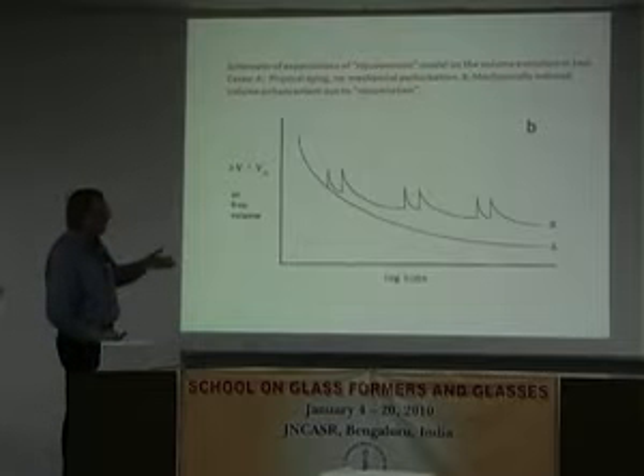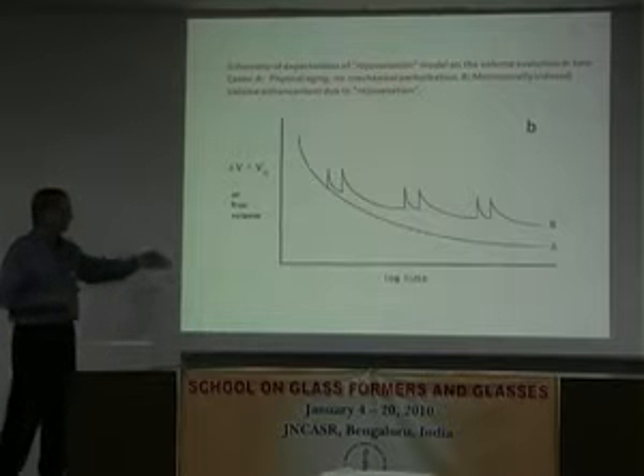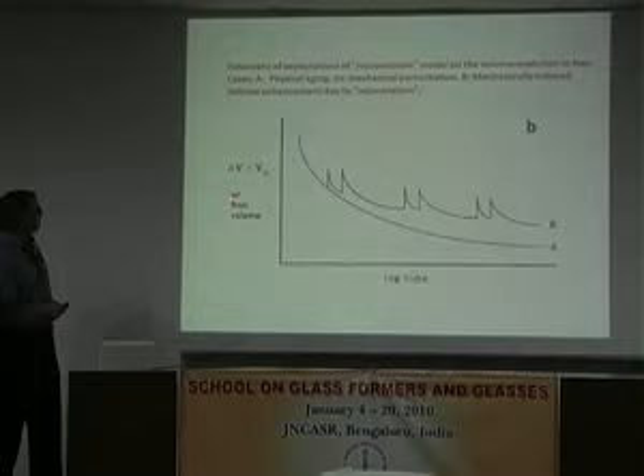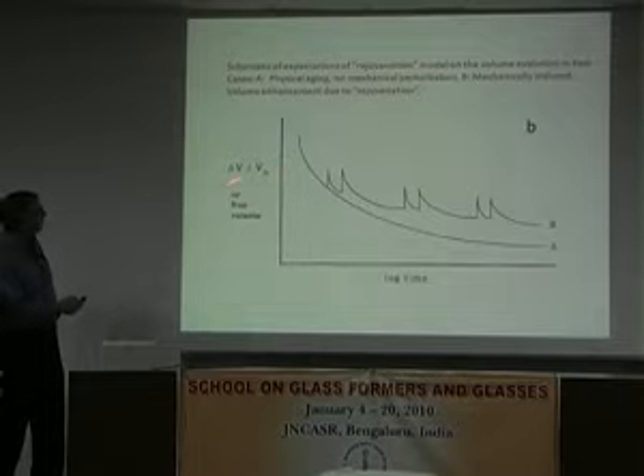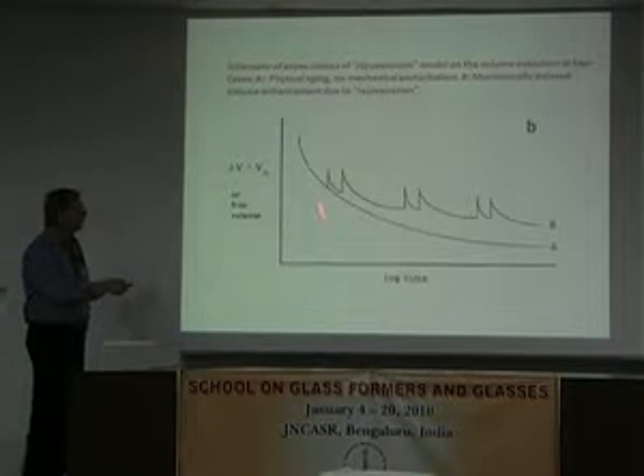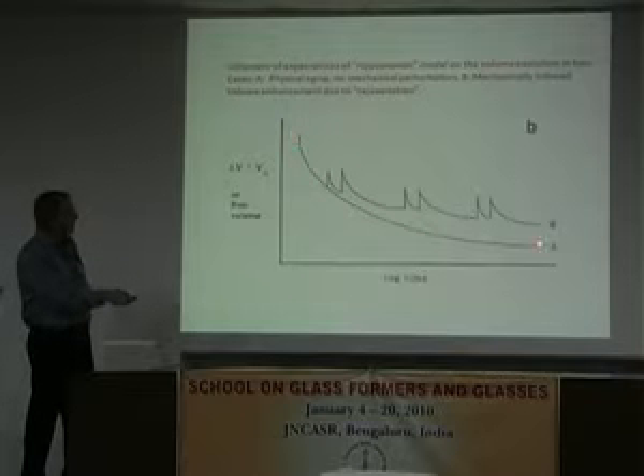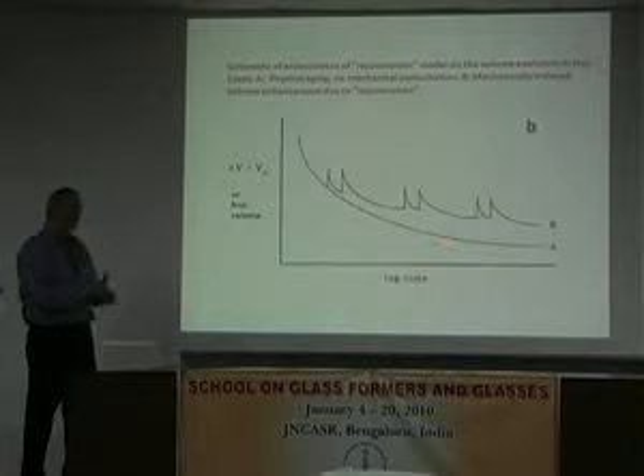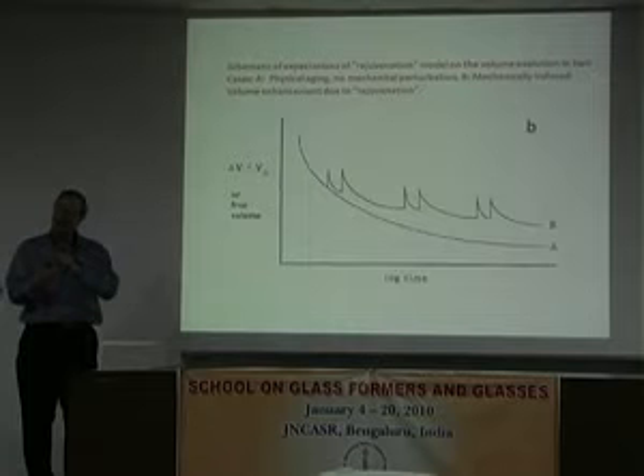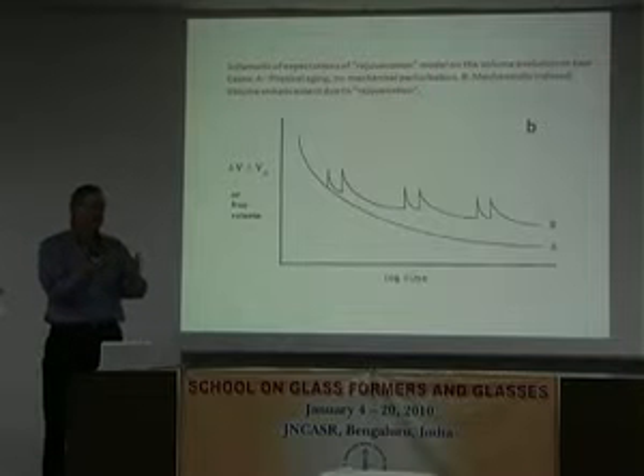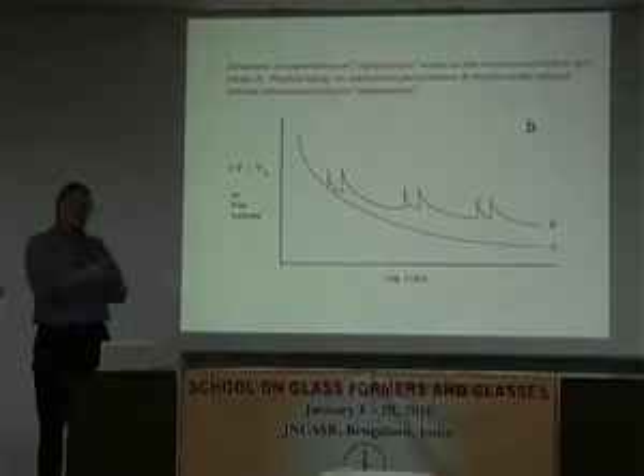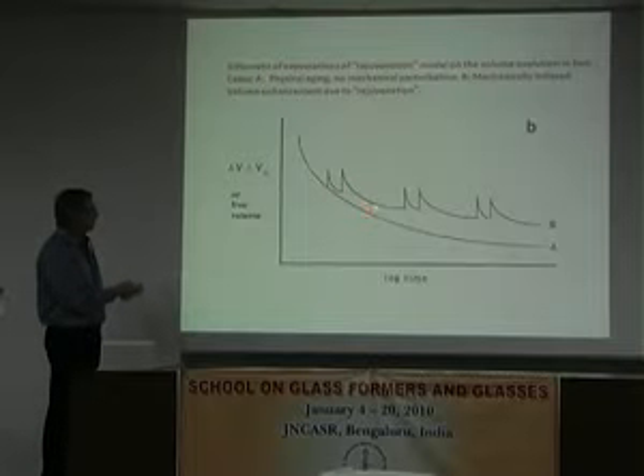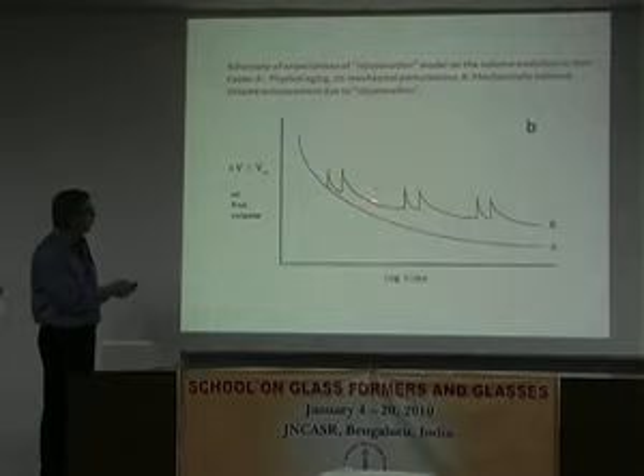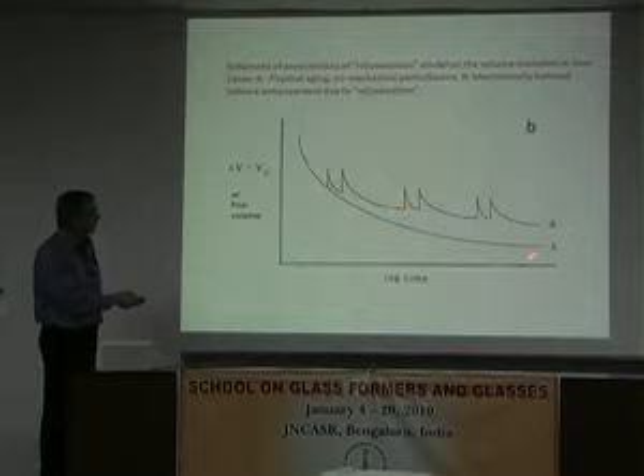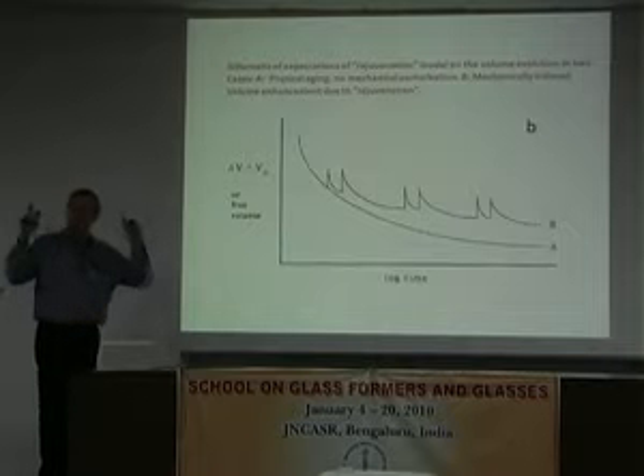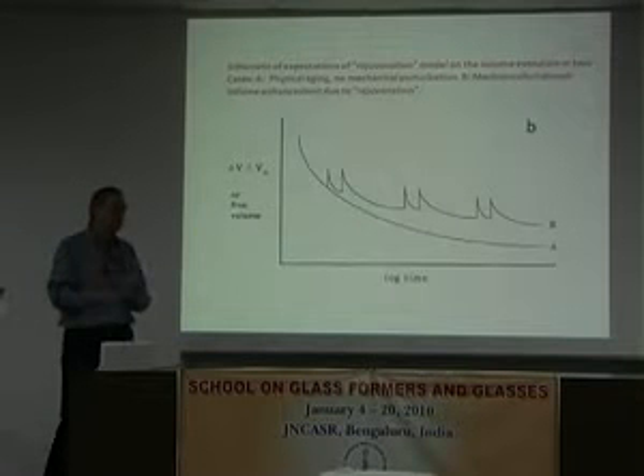And Struik had another interpretation. This is adapted from his plot. I just put it in terms of total volume; he did it in terms of free volume. But here would be the normal structural recovery after a quench. And he said, well, when I'm putting my mechanical deformation on, I'm putting in mechanical energy, and that's rejuvenating the material. And so as I load and unload it, it should not come back to the same baseline, because I, quote, rejuvenated the material or erased the previous aging.